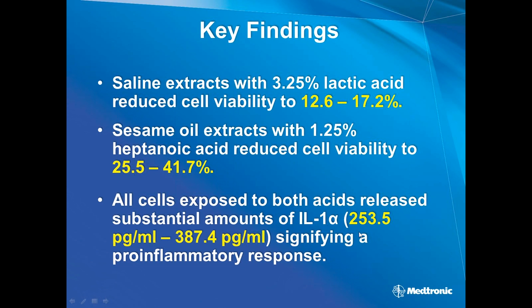And an interesting thing too is this down here talks about IL-1 alpha release, and it's just referring to heptanoic acid, as you saw in that previous graph. The heptanoic acid really caused those cells to give off a lot of cytokines, a lot of IL-1 alpha. Lactic acid, not so much. And we weren't really sure why that was the case. It was similar to the saline control, actually, and we wondered if lactic acid was having some effect on this ELISA assay, or if it was affecting the lactate dehydrogenase pathway, possibly.